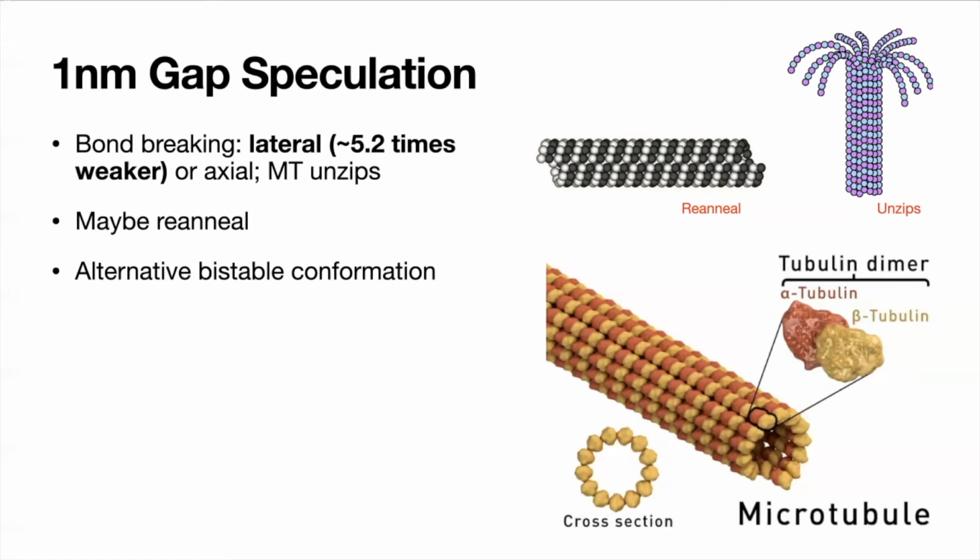So when we shift them, they can have weak interactions between each other and form an alternative stable conformation. Because it's identical, if you shift them, they're still the same thing. This is one of the reasons why we can see such jagged up and down tracks in the force indentation curve. The bonds between proteins first break and then reanneal and form a bond again.